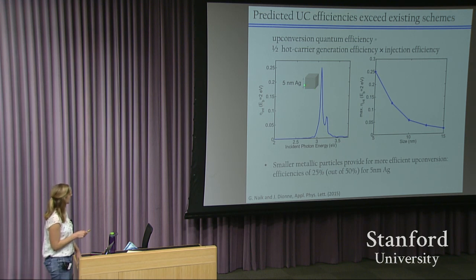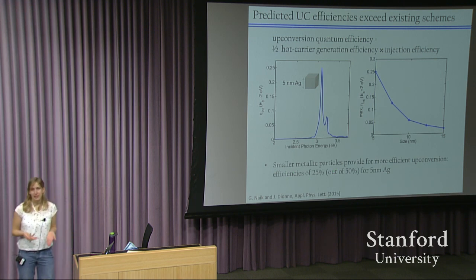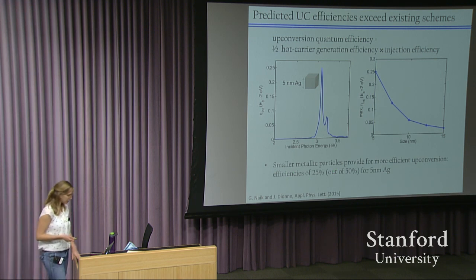And for example, in this particular 5-nanometer nanocube, you'll notice that we get quantum efficiencies of upconversion that are over 20%. So these small metallic nanoparticles provide generally for more efficient upconversion than existing material schemes. So we can get efficiencies of 25% rather than just less than 5%, and generally more like 1%. And like I said, my postdoc guru did the calculations at visible frequencies, but we can also tune these materials to work in the near infrared.